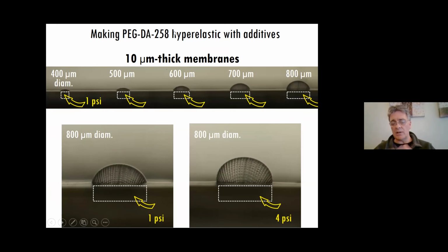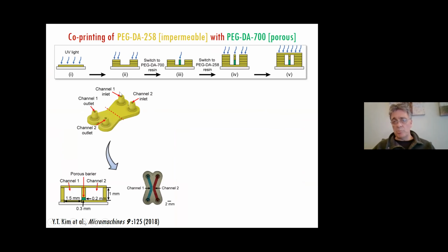We can also add additives to the membranes to make the PEG DA hyperelastic. Or we can also, like I was mentioning before, because these are acrylates, they are compatible with each other. So you can start building with a PEG DA-258, which is a plastic, and then switch to a resin that is a higher molecular weight PEG DA, like the 700 molecular weight, and that creates a porous structure within the channel, and they bind to each other. Then you can finish the structure with the plastic, with a PEG DA-258, and when you finish your channel, it's all embedded inside, and so you've created a barrier inside between the two channels that is porous in between.